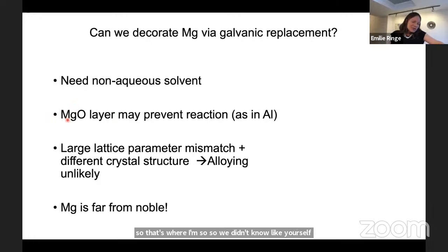Another problem we were really worried about is that this magnesium oxide layer might prevent reaction, and we have seen that significantly in aluminum, where galvanic replacement of aluminum has eluded us for the longest time while we were at Rice.